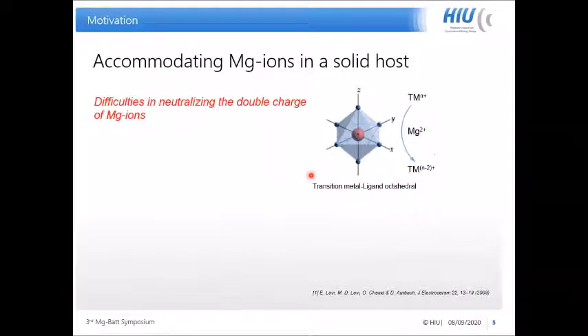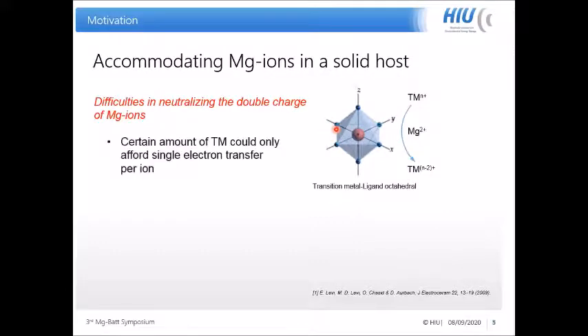But I would say, as Brian pointed out before, that magnesium mobility is not the primary limit or might not be the only limit for reversible magnesium storage. In fact, neutralizing the double charge of the magnesium ion is also not as straightforward as we expected. Especially if we look at transition metal compounds, if one magnesium comes in, we have to change the oxidation state of the transition metal by 2. So we need to know that not all transition metals could afford a change of the oxidation state by 2.